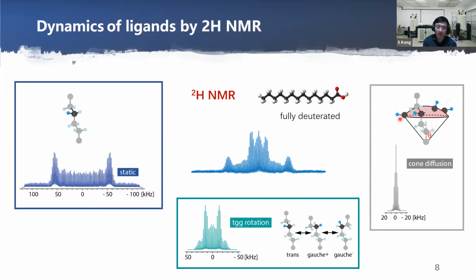So let's look at the ligand-ligand interaction first. The intermolecular dispersion interaction is actually very weak, and it hardly affects the chemical shift of NMR signals. So we decided to study the dynamics and get an indirect measurement of this interaction. Deuterium NMR is probably one of the most convenient strategies to study the dynamics in the solid phase. For some ligands, the deuterated version is commercially available. So we can put these deuterated ligands on the surface of nanocrystals and do deuterium NMR.